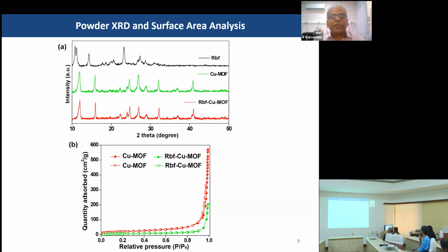If you look at the powder XRD patterns of pristine copper MOF and riboflavin-modified copper MOF, we can understand that the patterns are very similar, so there is no change in the crystal structure of the copper MOF even after its modification with riboflavin.